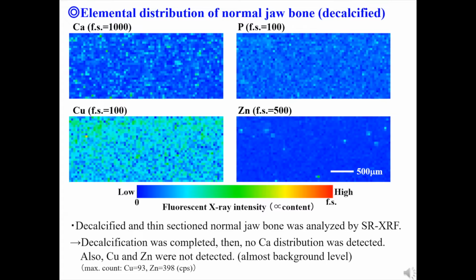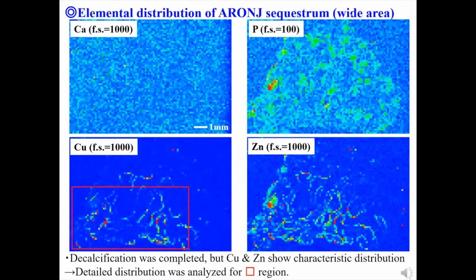In contrast, the ONJ sequestrum showed quite characteristic images. The specimen was completely decalcified, therefore, no calcium was detected. However, copper and zinc showed clear and characteristic patterns. This white bar shows 1 mm. Those images are the macroscopic images of the whole specimen. The next slide shows the detailed distribution in this red rectangular region.